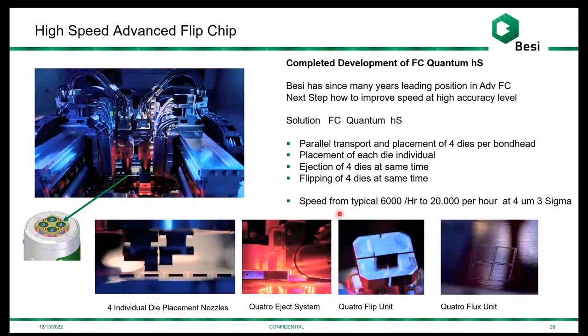And then at the end of the day, we have typically a need for high precision flip chip attach for mass reflow kind of interconnect systems. These typically don't require quite as accurate placement, so something in the range of 4 micron is adequate. However, speed and cost of ownership is really critical. So for these applications, we've developed a new system that enables us to pick 4 die from the film frame in parallel and then place.